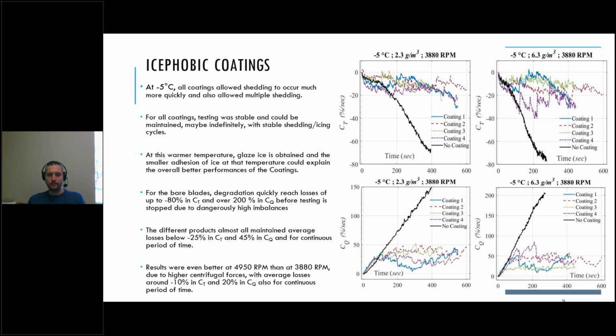And what occurs then is that we get some accumulation-shedding cycles. So small accumulation, then there's shedding, the performances increase again, then the accumulation is pursued, so the performances decrease again until another icing cycle and so on, and we can almost pursue testing indefinitely for those cases. So it means that the rotor could sustain those kinds of icing with the coating present, while only tolerating some slight performance losses during the icing events.